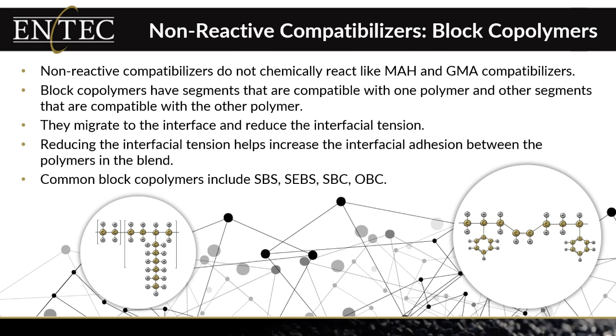And now if we look at block copolymers, again, these are non-reactive materials, but block copolymers have two or more segments of the backbone where at least one segment is compatible with one polymer and the other segment or the other block is compatible with another polymer. These products tend to migrate toward the interface between your two polymers, and they help to reduce the interfacial tension. And what that does then is it increases the adhesion between your two polymers. It can also provide for a finer dispersion in there and then therefore better mechanical properties.